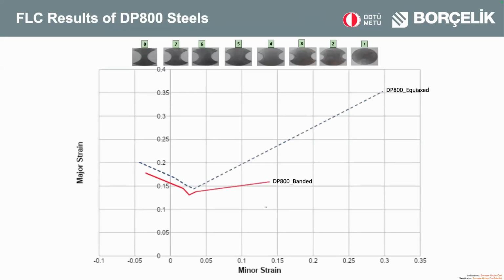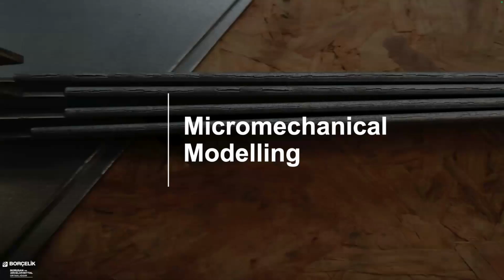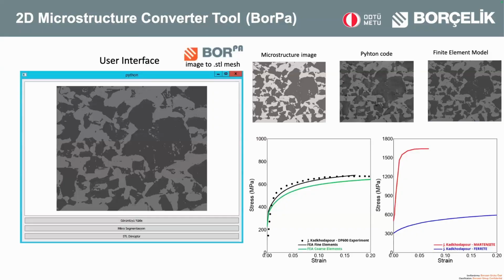And this is the FLC result of our specimens. There is not quite a big difference, but you can see that there are some differences. The DP800 with banded structure still has low formability. So to understand the mechanics behind these results, we want to investigate micromechanical modeling. But to do it, first we need an application to convert microstructural images to a finite element model. Our coworker, Mr. Akbaş, designed an application for this, and we call it BorPa. This application basically transforms microstructures into Python code, then a finite element model.